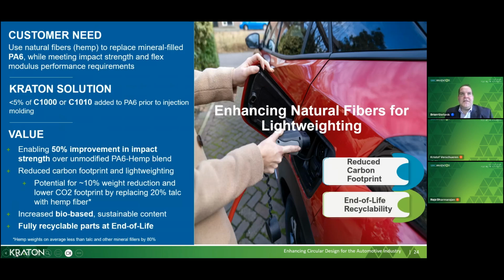So to give an example, we had a customer looking to replace talc-filled PA6 to achieve weight savings and to meet carbon footprint goals. And so the solution was natural hemp fiber. And to make up for the loss of impact and stiffness, we recommended 5% or even less of the C1000 and C1010. And the final product only used 3% C1000. But the surprising effect was that we saw a 50% improvement in impact strength, 10% weight reduction, and obviously a lower carbon footprint. So the additional benefit from lightweighting design, you may be aware, is the improved fuel economy that we see on the road. Or in the case of electric vehicles, it can actually help extend the range of the vehicle.